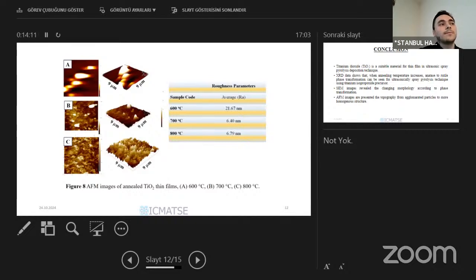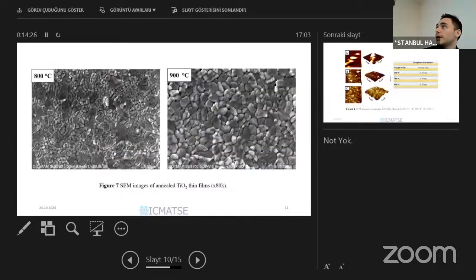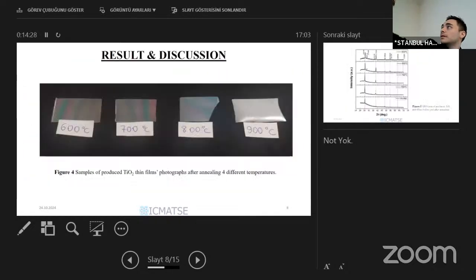So now I'm asking, is it possible to anneal above 800 degrees or below 500 Celsius? Above 800 degrees we also had 900 degrees centigrade annealing. You can see the difference on the surface here, there is a milky structure. AFM couldn't get a healthy surface morphology.